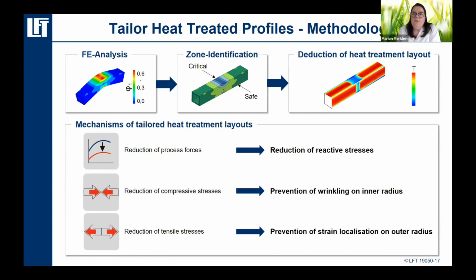areas. So if you have a look at the deduced heat treatment layout on the right, you see that, dependent on the layer where we have the tensile stresses and where we have the compression stresses, the heat treatment layout has to be different. And the big plus is that we are able to deduce mechanisms for how to design the heat treatment layout. And the three main and important aspects are the reduction of the forming and process forces by the softening of the material, the reduction of the compressive stresses, which means prevention of wrinkling, and the reduction of tensile stresses, which means the prevention of strain localization. And that works also with the profiles.